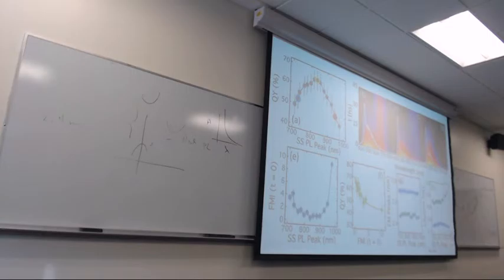And if you focus only on, like, 600 to 800, it will be different. There will still be several kinds of decays, right? From 700 to 800, you're probably going to see just two: one with about 10 nanoseconds, and one with 1 to 100 microseconds. This is the paper we did with Andre.